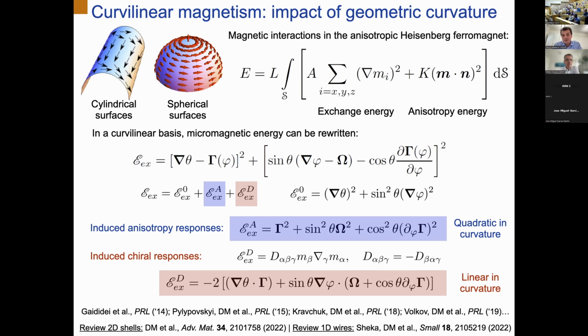So this is a slide based on the original work of Yuri Gaididei. He unfortunately passed away recently, but I would like to simply show his equations for this event. For my talk, it's very important simply to have the outcome of this analysis. If you have a geometric curvature in any kind of magnetic material, ferromagnet or antiferromagnet, geometric curvature will provide you with two effects. One effect is the emergence of an anisotropy response, and another one is induced chiral responses.